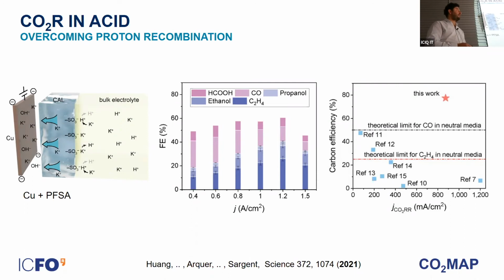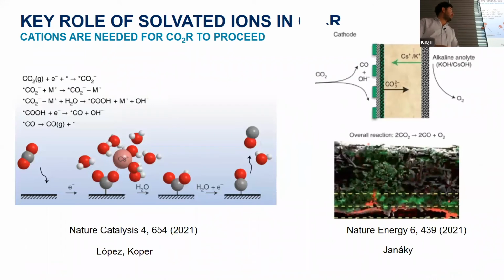In this work, if you count at the outlet stream of your electrolyzer the number of molecules that you generate and divide by the number of moles of CO2 that you put in the system, you get a number around 70%, which is above the theoretical limit for neutral media for CO2 electro reduction, both for CO and for ethylene. So this is the first demonstration of efficient CO2 reduction in acidic media, and as a consequence, efficient carbon use of CO2, so high carbon efficiency. And again, this is in line.